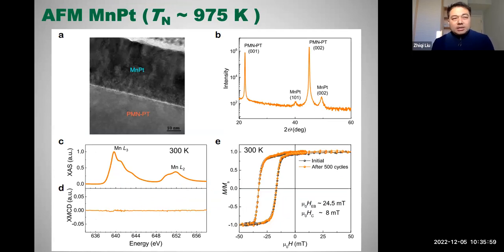After this work, let's think, because for antiferromagnetic materials, non-collinear spin structures are really rare. Most antiferromagnets exhibit collinear, just simple antiparallel spin structures. And we then thought about how the strain modulation effect works for just collinear antiferromagnets. So we continued to grow the collinear antiferromagnetic manganese platinum. This 50-50 phase is a collinear antiferromagnetic phase on PMN-PT, which is also a ferroelectric oxide.